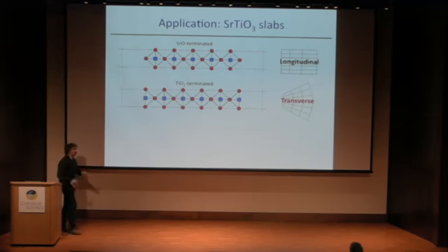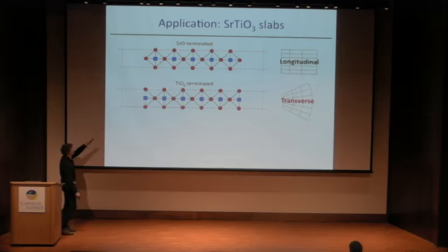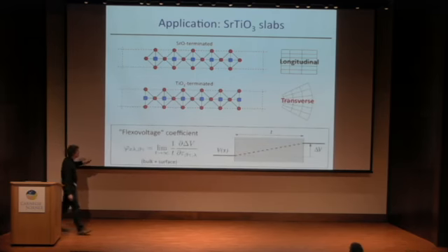Okay, let's go to the results. We went through the theory. We're all alive, I hope. So essentially, I wanted to show this surface dependence. So I took two slabs with different terminations. One is a Strontium Titanate slab with an SrO termination, the other with a TiO2 termination. I will consider these two types of strain gradients with full atomic relaxation, and I will look precisely at what I said before, the overall flexo voltage coefficient, which is the offset from one side to the other upon bending the slab.